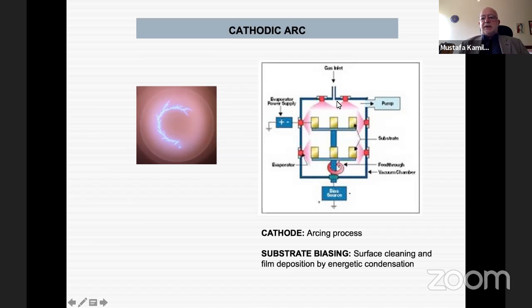So this is a schematic of a cathodic arc setup. These are cathodic arc sources, as you see, these pink and red parts. And we burn these cathodes by using a very simple power supply that we use in arc welding. So this is a high current, low voltage power supply. When we short circuit these two leads on the surface of the cathode, the arc starts to initiate and starts to burn. In this manner, we introduce into the environment the metal vapor that we want to work with.